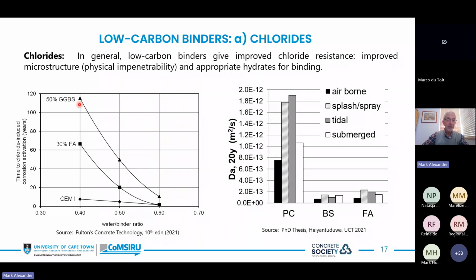The other materials, the blended binders, these are low carbon binders, maybe the 30% fly ash, not entirely yet, but you can see the huge benefit. And the reason for that is quite simple, that if we look at the long-term apparent diffusion coefficient, that's this parameter here, dA, at 20-year value, the diffusion coefficients in these blast furnace and fly ash concretes are so low compared with plain cement here. So these reduce incredibly with time. The microstructure is improved actually to such an extent that we get this huge improvement and hence a much, much longer life. And that's true for all the different marine zones with which we might be concerned.